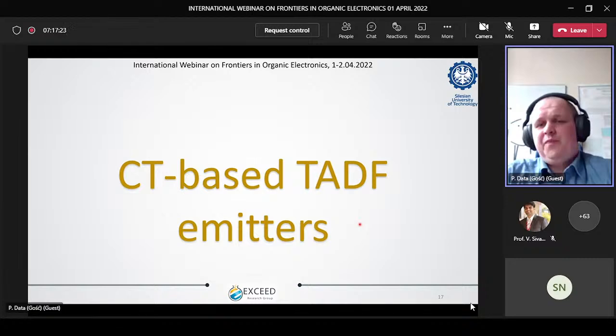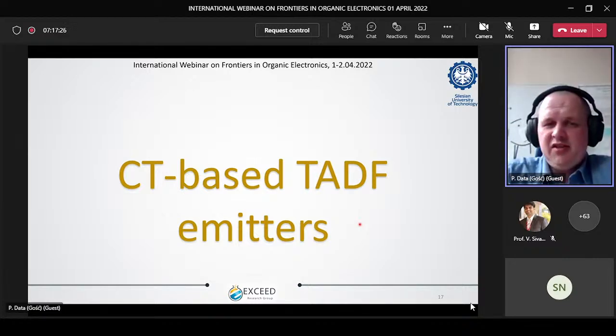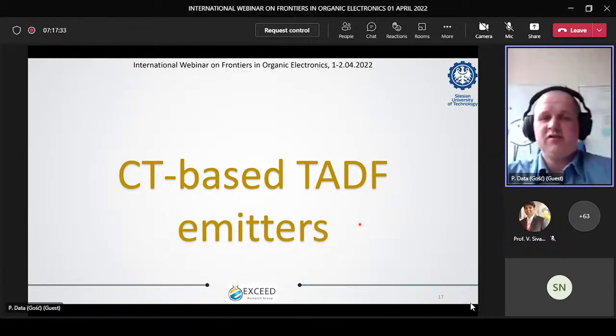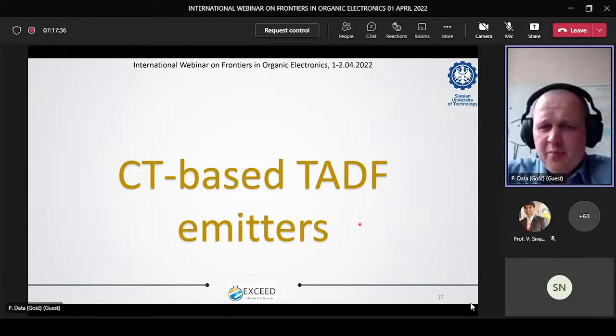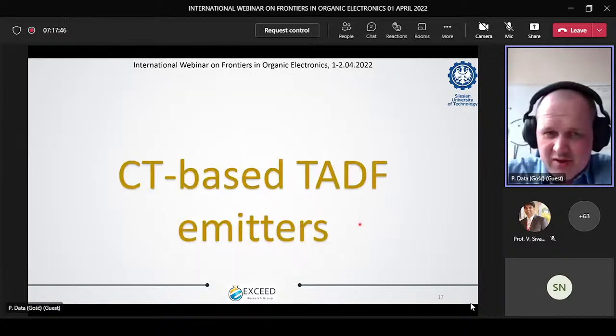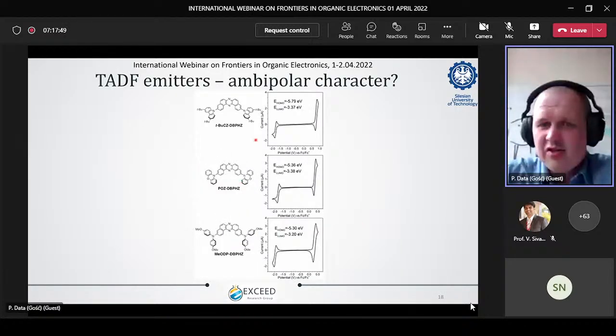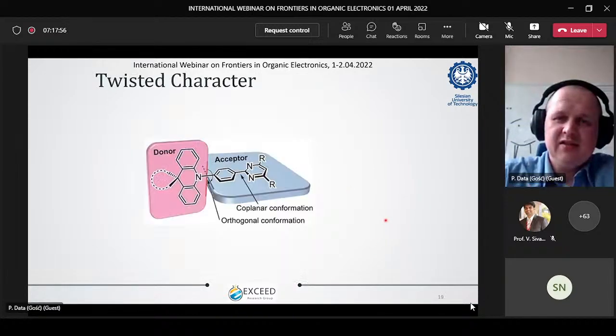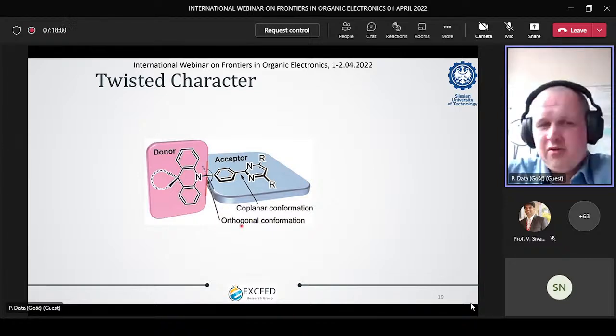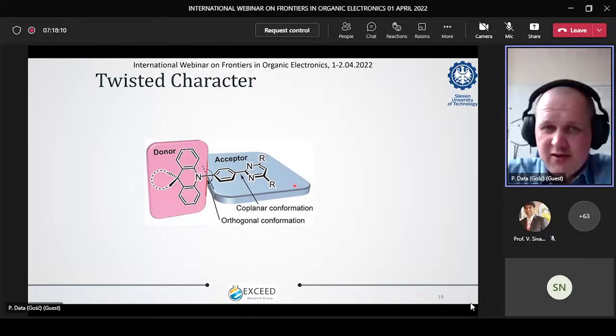Thanks to this analysis, we can estimate if we have CT emission or we don't have CT emission, if we have delayed fluorescence or we don't have delayed fluorescence. If we think about the TADF emission, we have two different types of emitters, CT-based emitters and non-CT-based emitters. In the case of the CT-based emitters, those are usually ambipolar emitters. They have ambipolar character. That's why we investigate that in the beginning. And how to get that? We need to have orthogonal conformation of our molecules. So they should be, like I would say, perpendicular, the donor to the acceptor planes, like you see here.